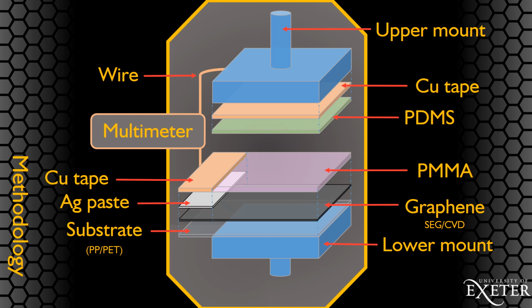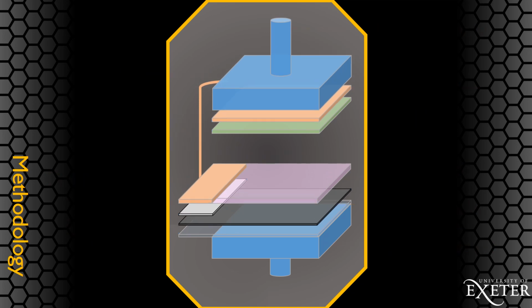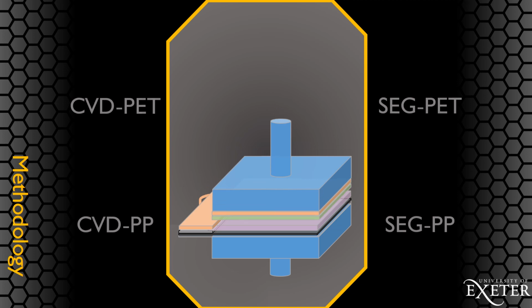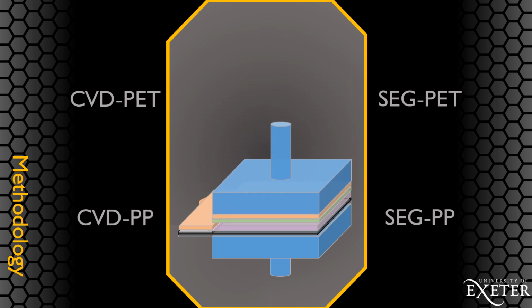The device is placed within a vertical sliding machine and is operated at varying speeds and distance separations. From this, we are able to test 4 devices by varying both the graphene and substrate type. These are CVD-PET, CVD-PP, SEG-PET, and SEG-PP.